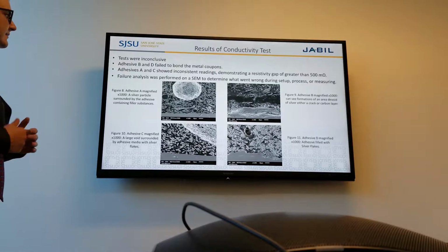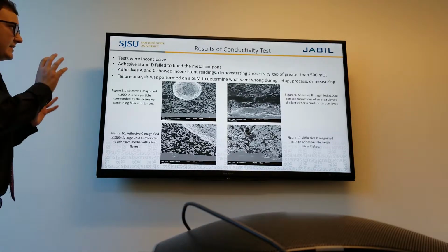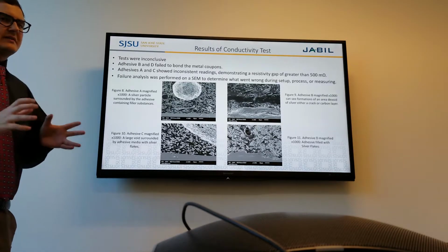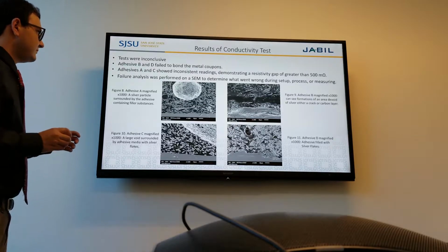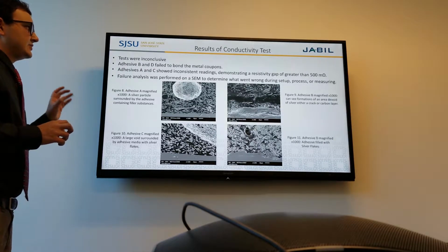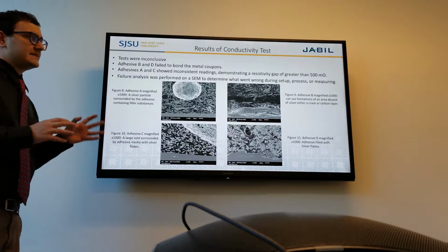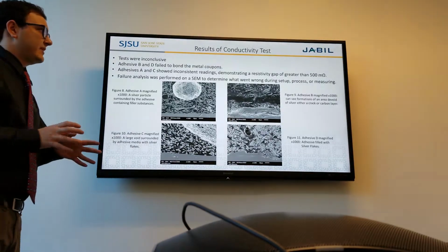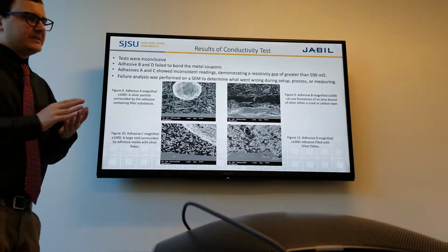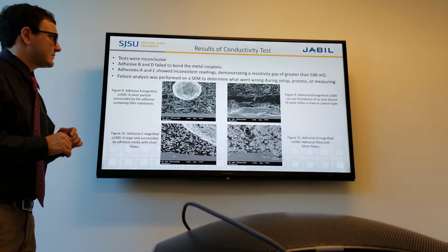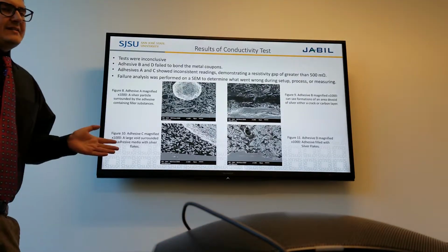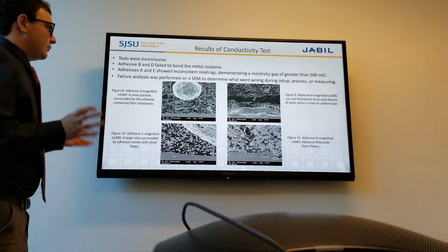Unfortunately, our conductivity test was inconclusive. The reason it was inconclusive is because adhesive B and D failed to bond to the metal coupons, while adhesives A and C showed inconsistent readings, demonstrating a resistivity gap of greater than 500 milliohms and a base resistivity much higher than 10 milliohms. So failure analysis using a SEM was performed to determine what went wrong.